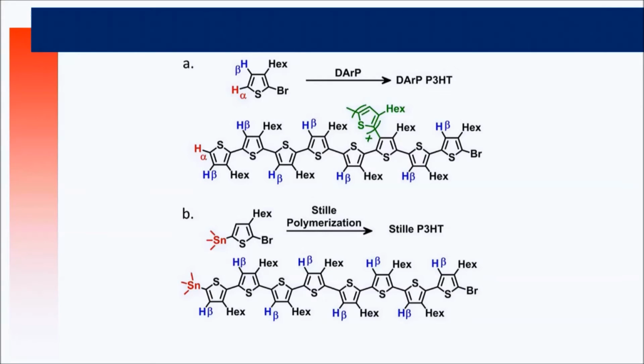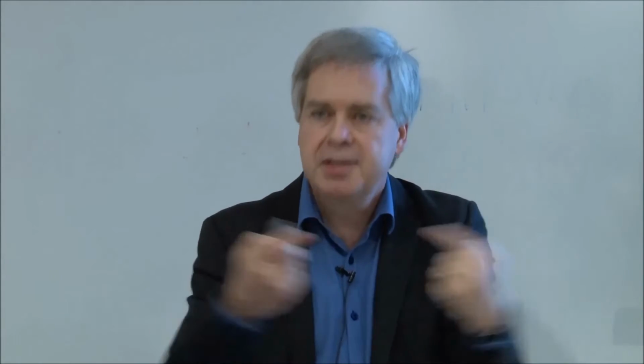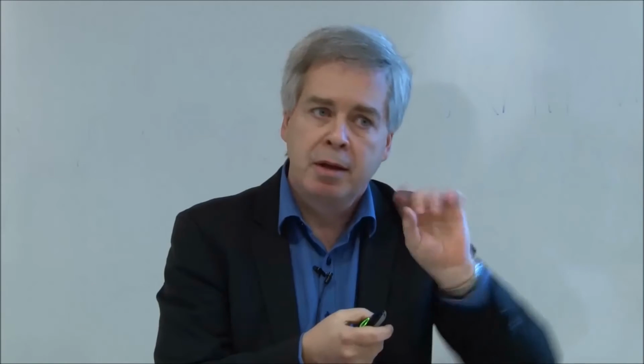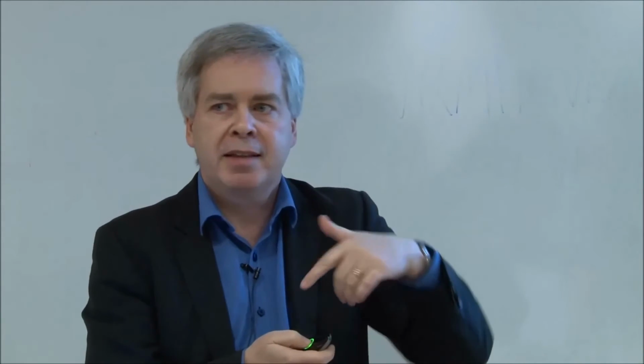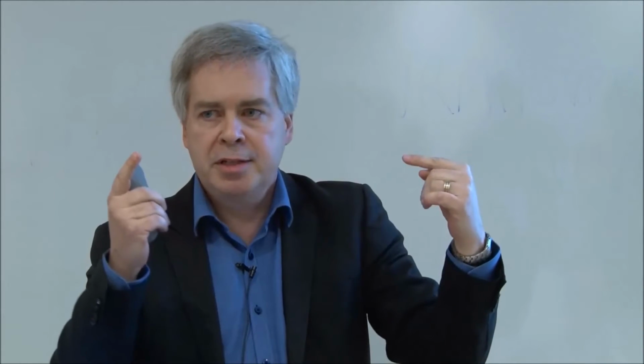Another way to see it: if you make P3HT from Stille coupling, let's say, the beta positions are not reactive, because coupling will just occur where you have a bromo group and a tin group. But for direct arylation, the number of alpha protons will decrease as a function of the molecular weight, and the probability of branching will increase with the molecular weight, because the number of beta protons will increase compared to the end groups. So it's not surprising that when you increase the molecular weight, the selectivity will decrease, and you will get branching and cross-linking.